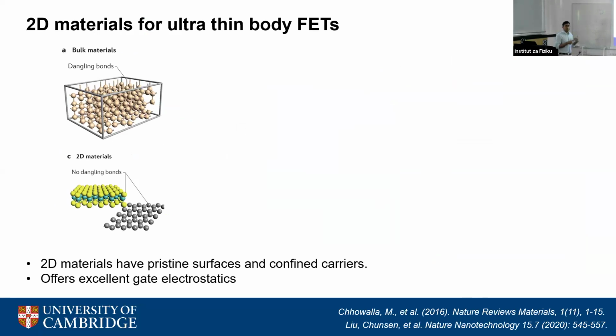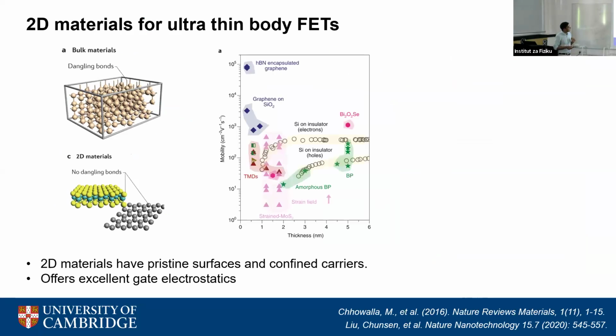2D materials are quite promising because they are atomically sharp. You have no dangling bonds. And this is a plot which shows what happens to the mobility of carriers in a material as you reduce the thickness. You can see these materials have reasonably high mobility even at lower thicknesses. And because the carriers are confined, you can in principle control them very well with the gate, because they're not distributed in the whole three-dimensional bulk as is the case in silicon.